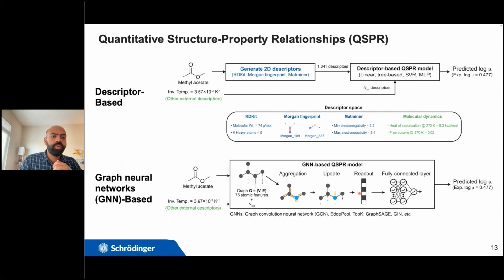One is the descriptor-based approach, where we generate, for example, RDKit descriptors, the circular fingerprints, also known as the Morgan fingerprint. We generate Matminer stoichiometric-based fingerprints and also molecular dynamics-based fingerprints. I'll go into a bit more detail about the molecular dynamics-based descriptors in the next slide. But these are basically quantities like the heat of vaporization and the free volume that we calculate for the amorphous system of the molecule. And finally, we also looked at graph-based approaches, which don't involve any explicit descriptor generation.